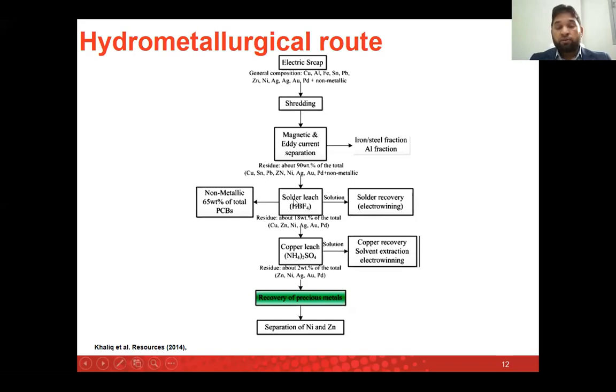So the residue of the solder leach contains copper and the other precious metals. Then you can do a further copper leach treatment, and the solution is sent for copper recovery through the solvent extraction method. Then the residue of the copper leach will have zinc, nickel, silver, Au, and palladium, from where you can extract the precious metals. And at the end, of course, you will also have nickel and zinc.